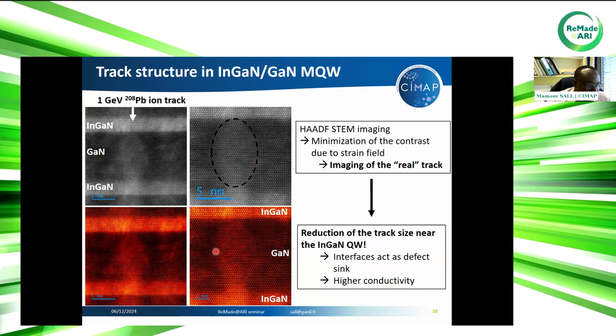So this reduction of the track size might be due to the fact that the interface, like many interfaces in different materials, acts as a defect sink. But another possibility is that, as you know, in multi-quantum wells we confine the carriers in the quantum well, so we increase the conductivity of the material near the interface of the quantum well. If we get back to the way tracks are created, there is a melting. As we increase the conductivity at the interface, we will dissipate the heat. So this will result in a more resistant material at the interface here.